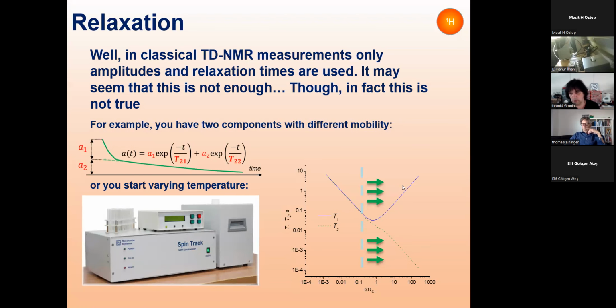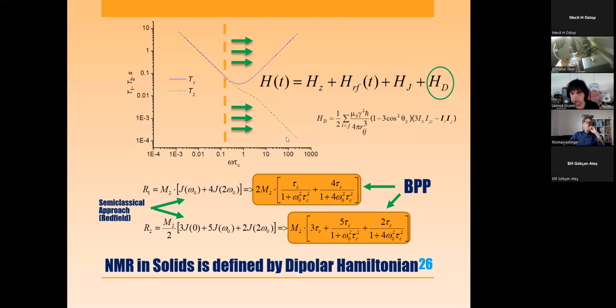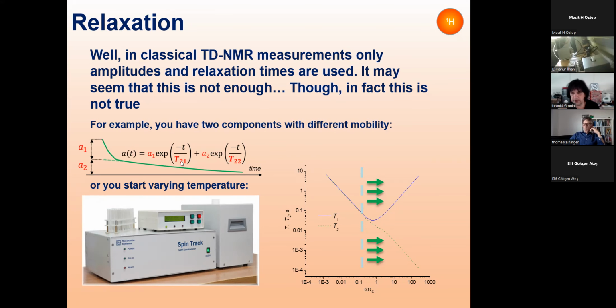Well, so we can talk about relaxation time, and it looks like you put a sample and you measure only one parameter. This is not in fact true, because most samples are heterogeneous, they might have different fractions, like you just saw from the ESMA experiments. For example, a starch sample contains a solid fraction with a short T2, and more or less water with a long T2. We measure one sample, and even with the simplest approach we get 2 relaxation times and 2 populations. So you can immediately think about, for example, humidity, or if it's not water, oil, or even some short molecules within the big polymers and so on. So it is not true that time domain NMR is low informative.